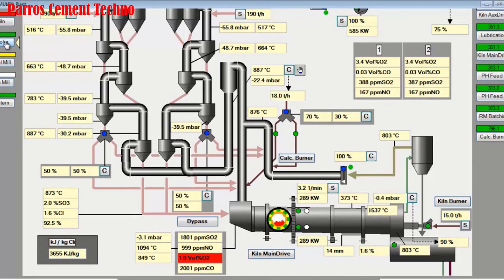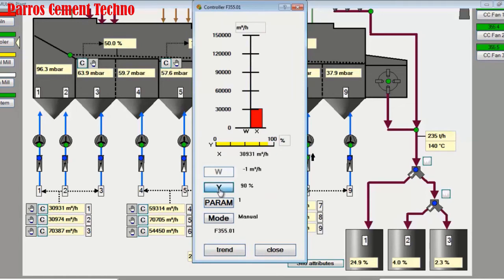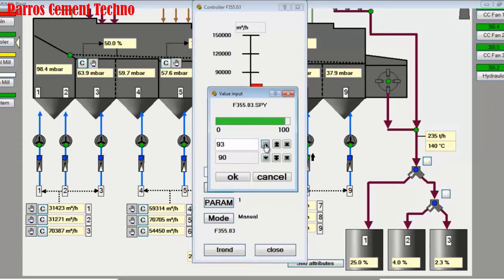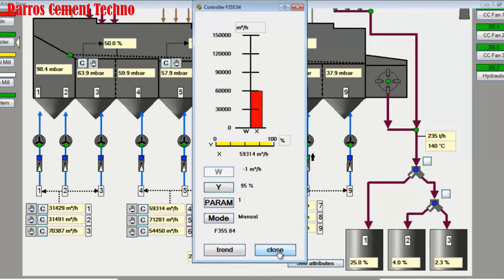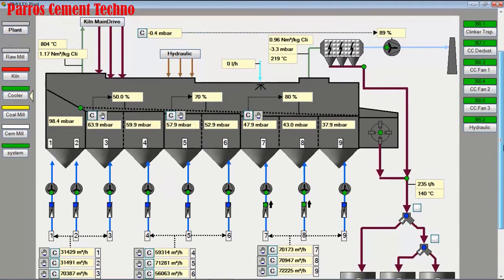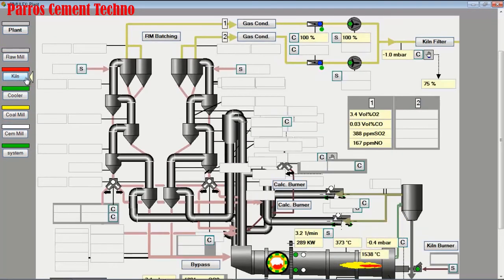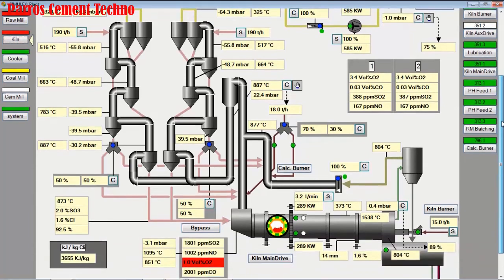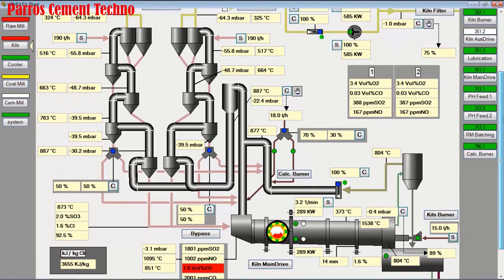To add O2 we add cooling air. We increase each cooling fan for grate 1 by 5%, and also increase the grate 2 cooling fans by 5% each to 95%. The total cooling air reaches 2.1 normal cubic meters per kilogram of clinker. Returning to the main kiln monitor display, O2 at the kiln inlet is still 1% and free lime is still 1.6%.